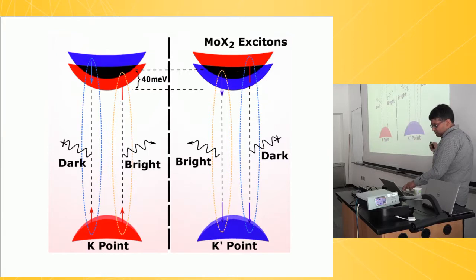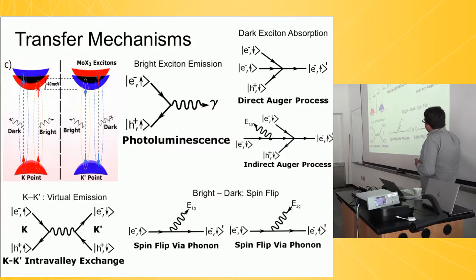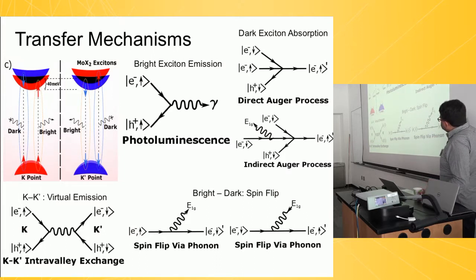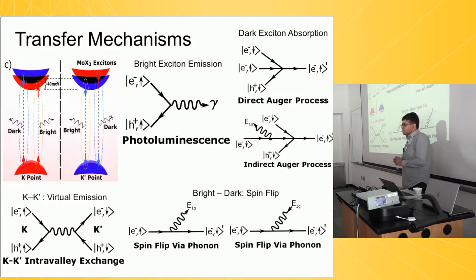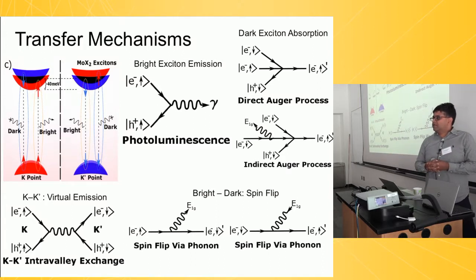So here, that's once again this picture. And one of the things that defects do, especially point defects, is that point defects can couple different valleys. So a point defect can transfer any momentum to an electron. And so what it can do is take an electron from the k valley and send it to the k prime valley. And generically, there are many different mechanisms by which it can do this, and this kind of business is not good for observing an effect like what I talked about earlier.